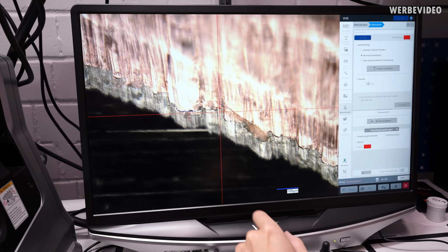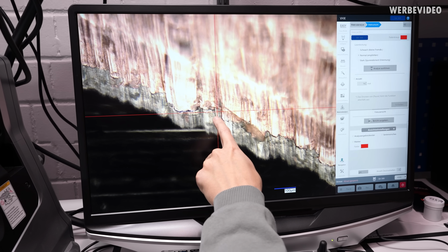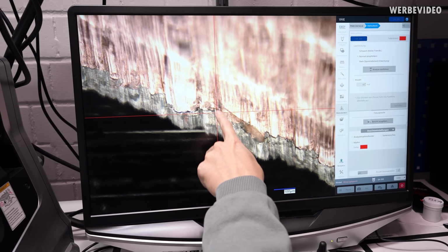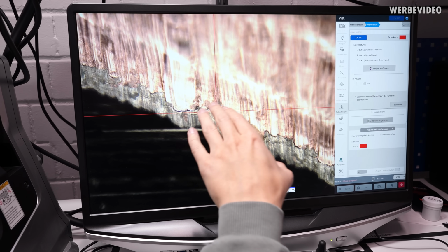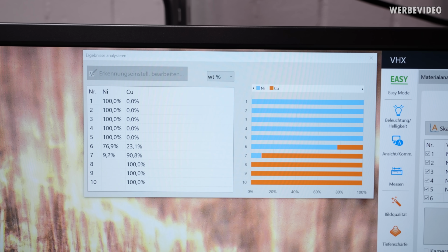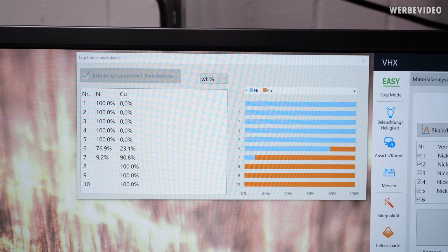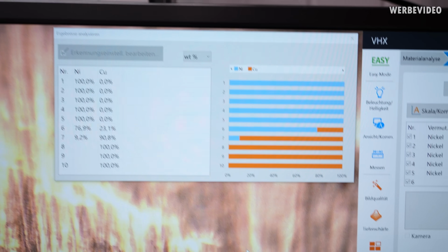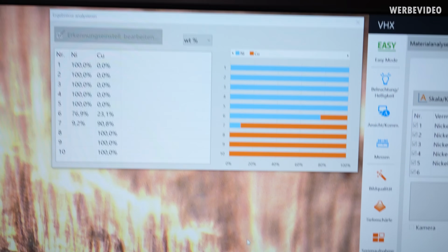I'm trying to put the focus, or the laser point, directly on the edge where the nickel layer ends. And then we have the copper underneath, and then I will do the same multi-layer analysis. And this confirms our guess. We still have like 4 or 5 times nickel, and then underneath we have already like 100% copper.